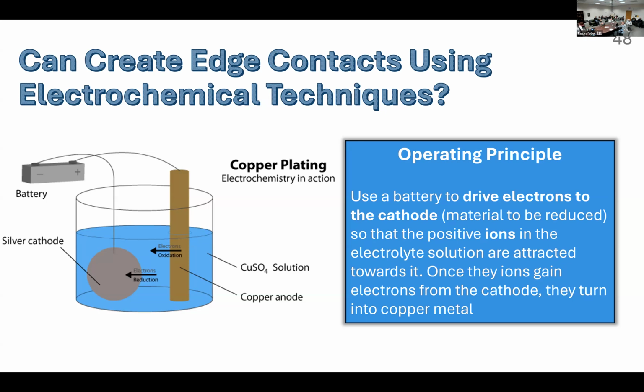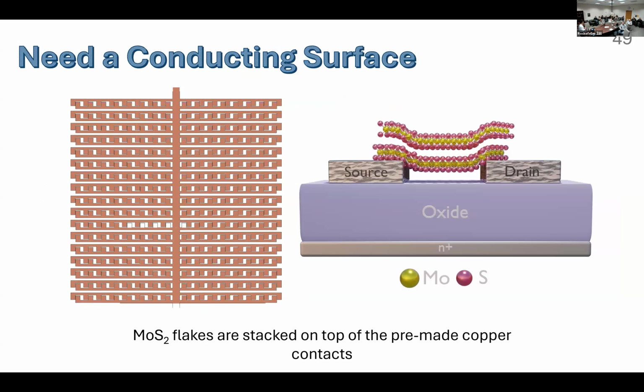However, you might notice that in order to do this, you need to have a metallic sample, both for the metal that you want and where you want your metal to be deposited. But if you recall from my device structure, our devices are on top of an oxide layer, which is a very insulating layer. So in order to be able to do this process, we need to ensure that we have a conducting surface. So I created a mask so that I could have an array of transistors that I could easily cleave in the middle, along here and here, to then separate after the electroplating, so I can go ahead and do electronic measurements.